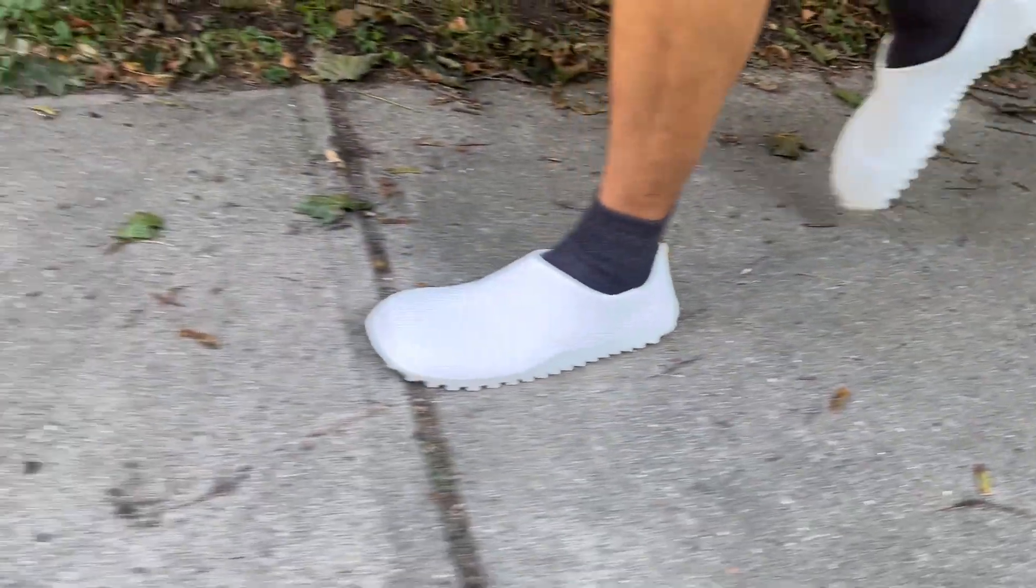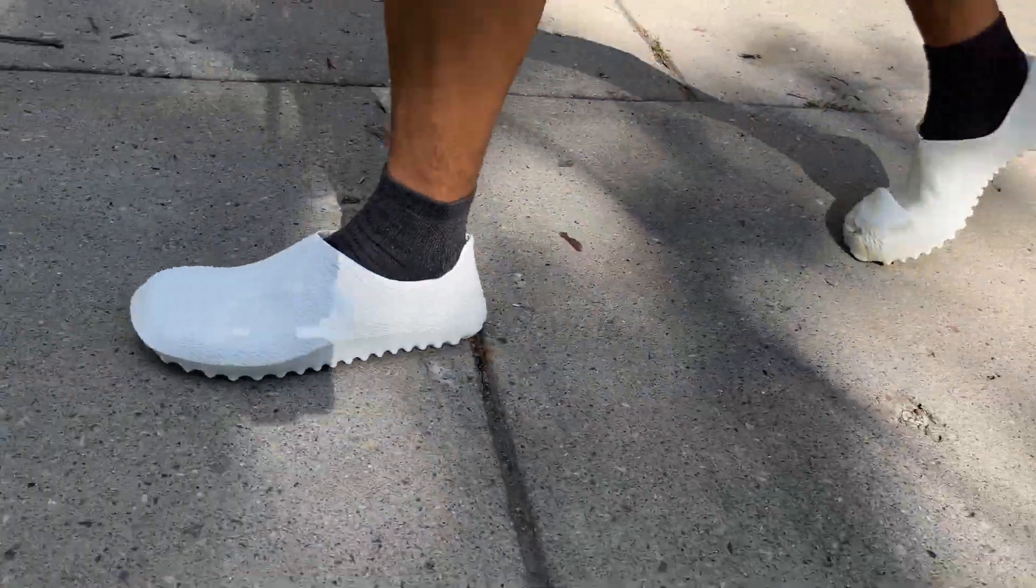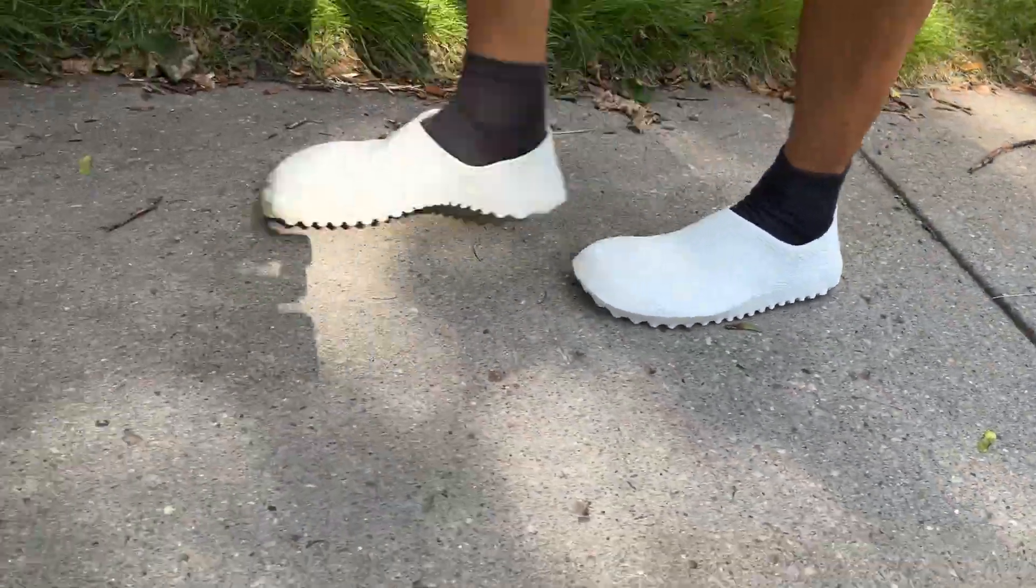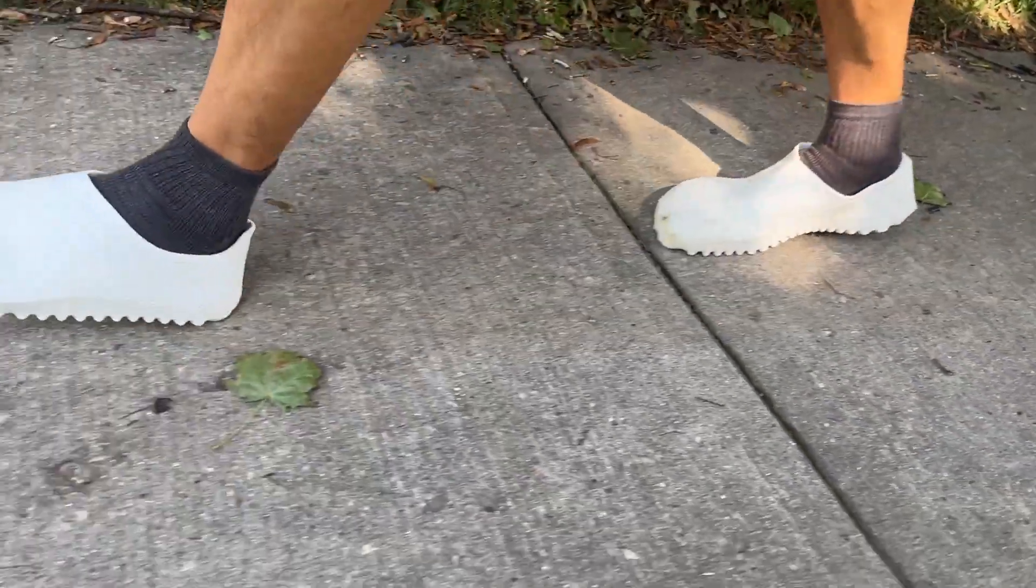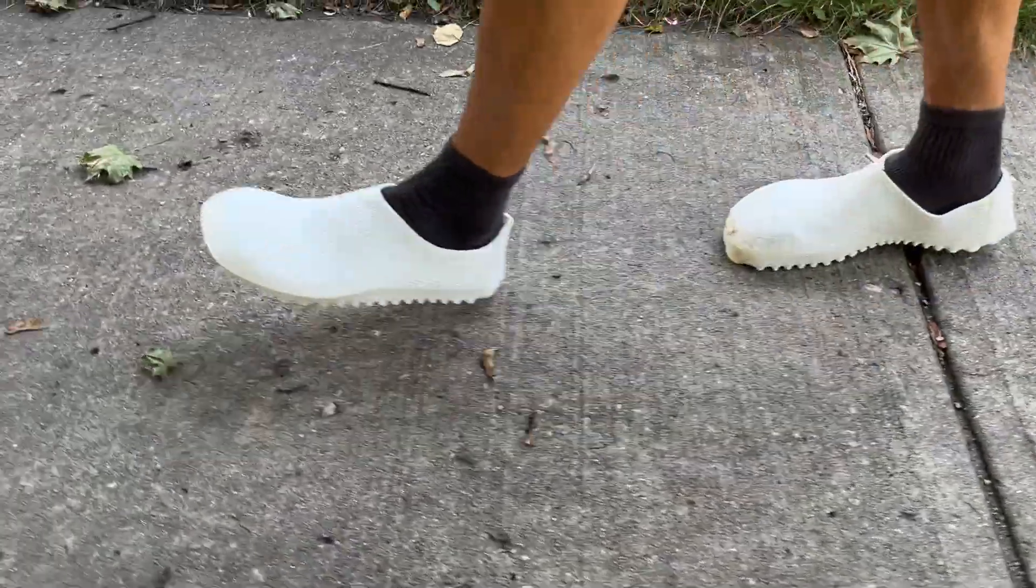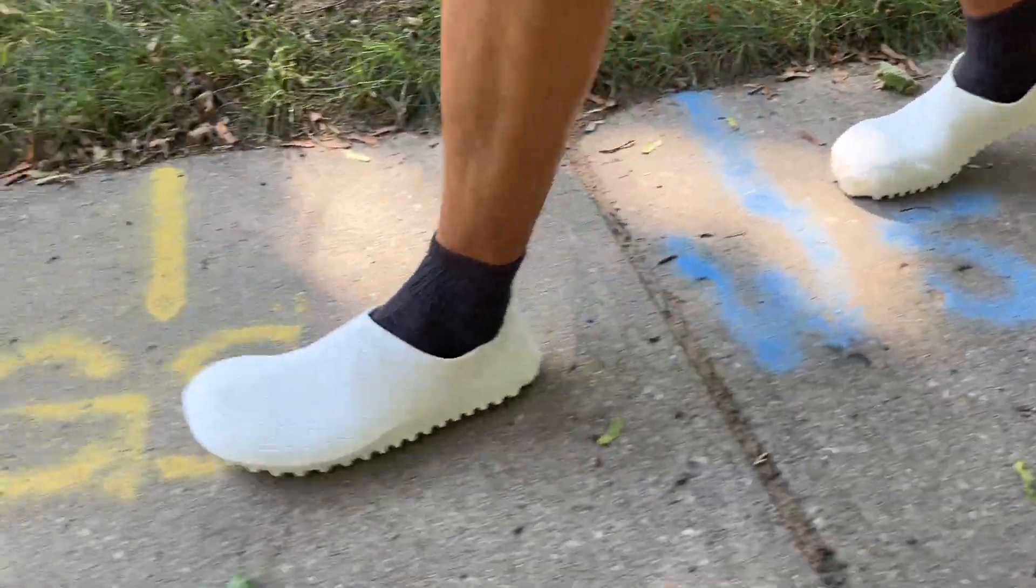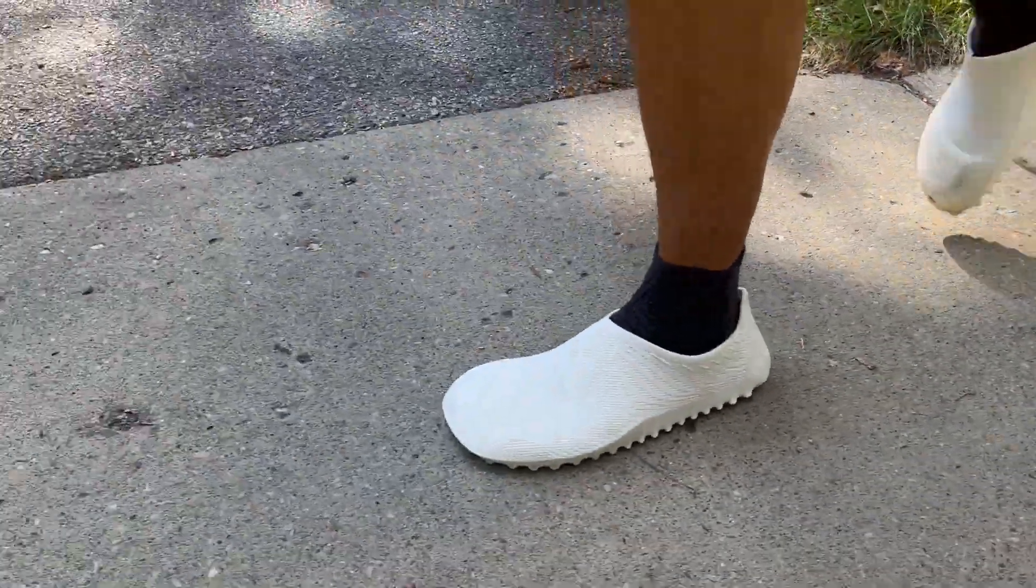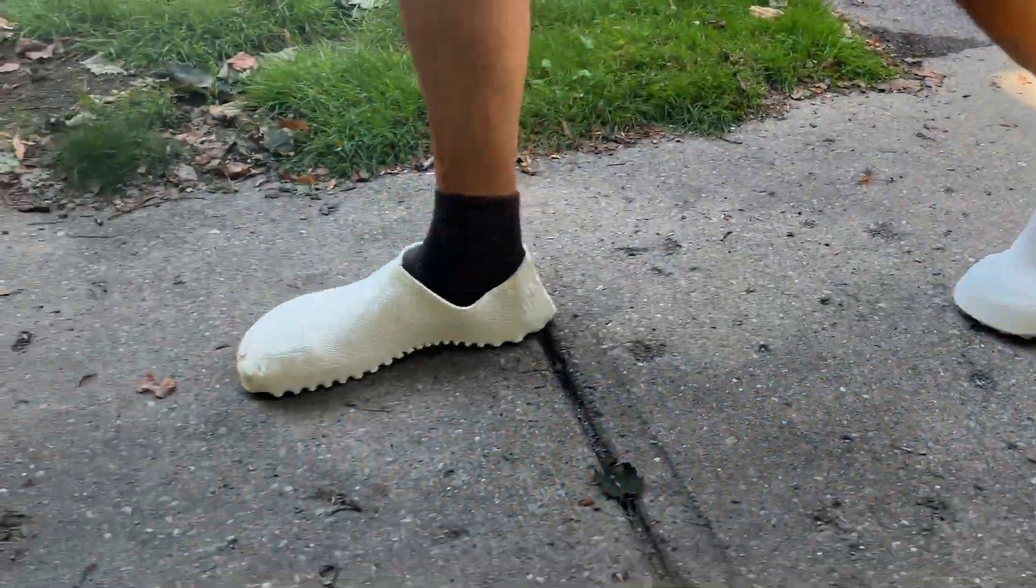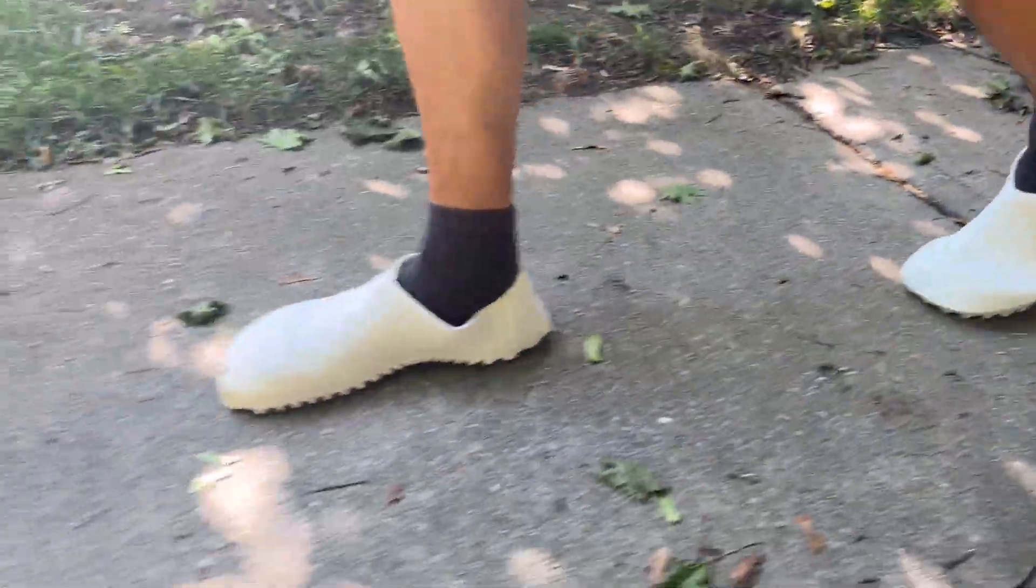Another characteristic of the material that surprises me is the stretching and compression with use. After maybe 20 or 30 kilometers, I am finding the shoes to be looser both because of some stretching of the upper and compression of the sole. I had always thought the TPU and lattice structures would somehow be less subject to plastic deformation than say EVA foam, but this wasn't the case. That being said, this kind of deformation can be a good thing as the shoe is broken in essentially. You just have to make sure that the fit is a bit snug when fresh off the printer.